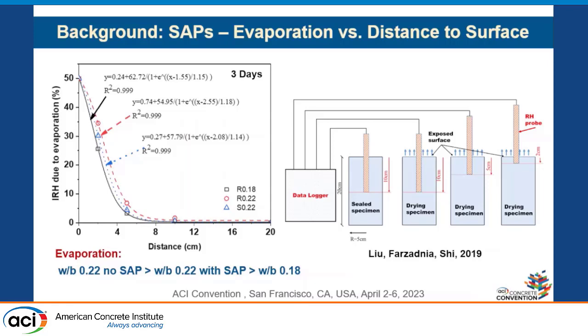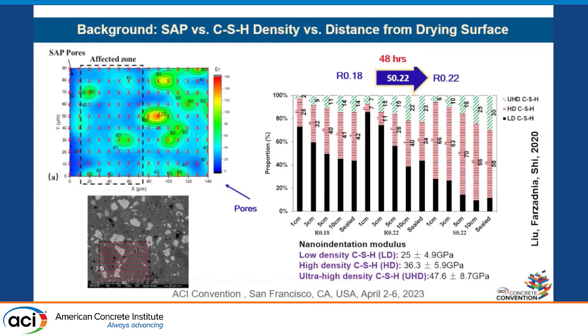We figured out that SAP has an important functionality in controlling evaporation. If we have the same water to binder ratio in concrete, for example, here we have water to binder ratios of 0.22, 0.18, and 0.22, and when we add SAP, it reduces the evaporation significantly. This control of evaporation can lead to formation of higher density calcium silicate hydrate, or ultra high density calcium silicate hydrate.